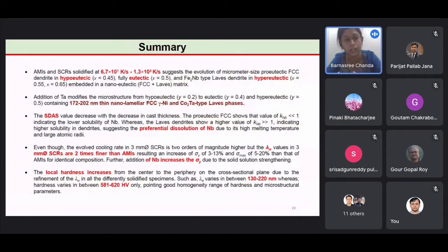So from here we can conclude that we have successfully prepared two series of eutectic high entropy alloys with niobium and tantalum addition. The microstructure varies from hypoeutectic to eutectic and hypereutectic. Preferential dissolution of niobium due to its high melting temperature and large atomic radii can be seen. Also, the niobium increases the yield strength.